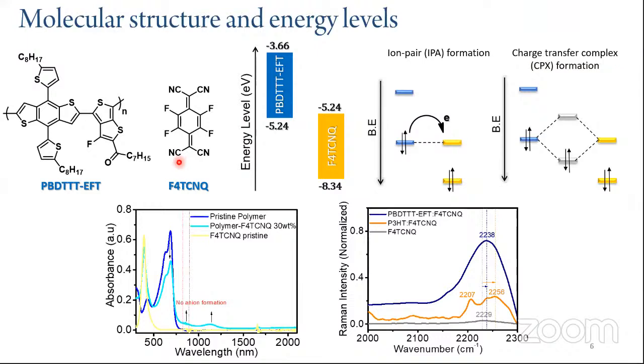Yes, sir. Here this F4TCNQ dopant is a strong acceptor having 4 fluorine atoms. It is well known to have good charge transfer properties with the polymer. And coming to the other polymers like thiophene-based P3HT or PBTTT, they are already well studied and saturated, and donor-acceptor type polymers have not really been explored in the field of thermoelectrics.